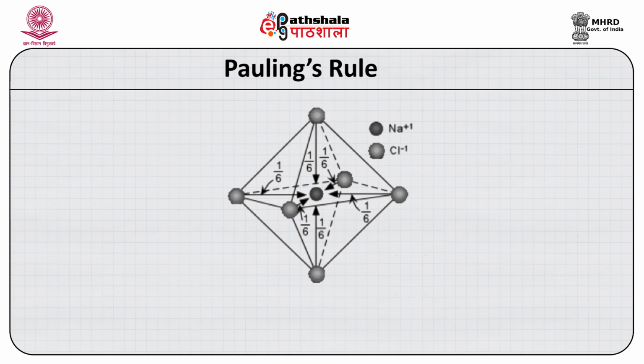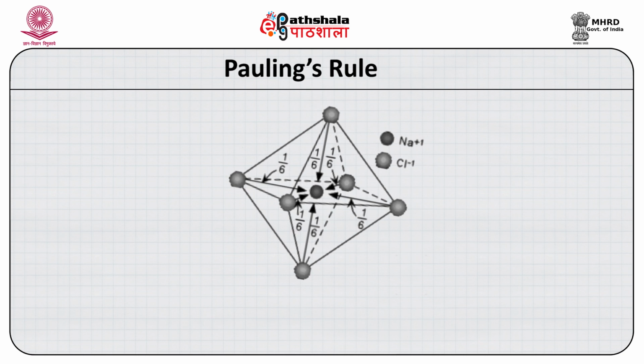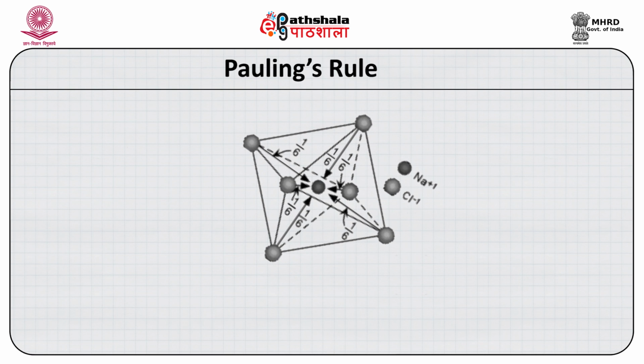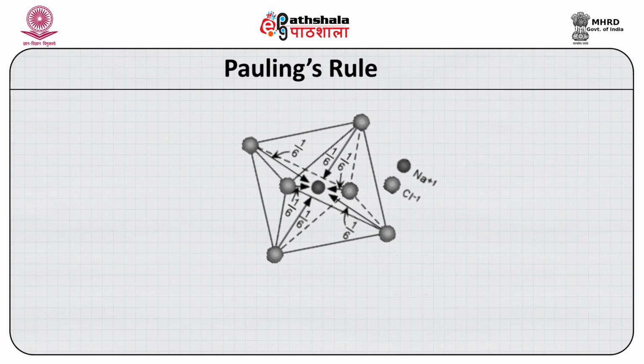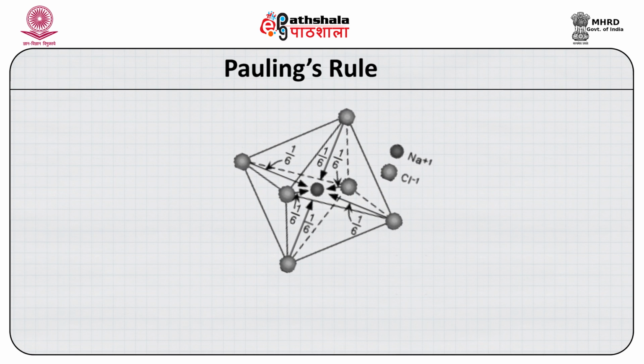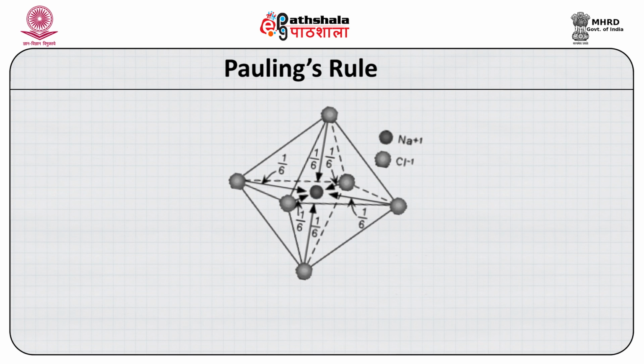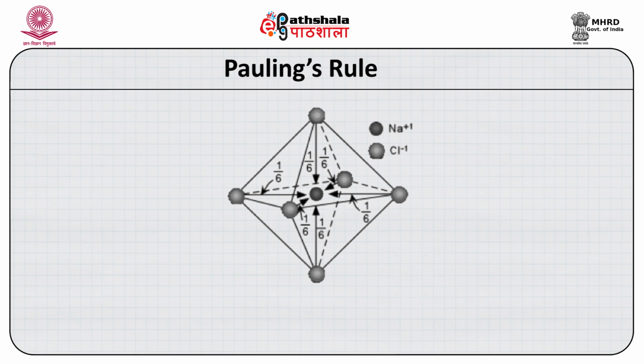Similarly, each chlorine ion is surrounded by 6 sodium ions in octahedral coordination, and again 1/6 of a positive charge from each sodium reaches the chlorine ion, and thus the Cl ion also receives 6 multiplied by 1/6 positive charge. However, this situation may not be similar in other structures.